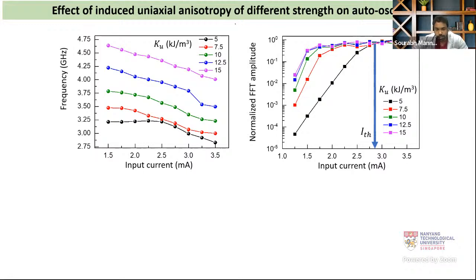There is also another important result in the right side graphs: as we increase the anisotropy energy density, the Ku value, the threshold current for the auto oscillation is significantly reduced. As you can see from these graphs, for lower anisotropy, the auto oscillation has not started yet, but for the same input current, for higher anisotropy, the auto oscillation has started. That means we are able to achieve a low threshold input current value for auto oscillation, and this gives us the opportunity to design low input power oscillator devices.